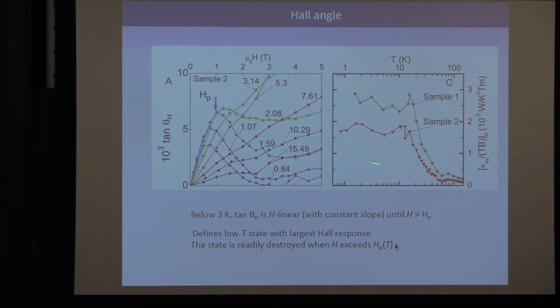Okay, so one way to analyze this is to look at the thermal Hall angle, right? Take the ratio of the Hall current to the longitudinal current. So that's a measure of how much deflection you get in the magnetic field. And it's fairly large. Although it looks smallish, right, 5 milliradians, it's still quite large in these kinds of measurements. So you see that as at the lowest temperature, 0.8, it increases linearly and then starts to come down.